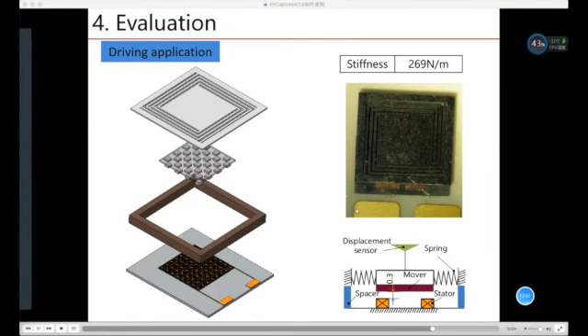In order to test the application of this actuator, we apply this mover with the planar spring like this, and then assembled a micro actuator. The planar spring stiffness is 269 Newton per meter, calculated by the finite element method. This shows the picture. And then to measure the displacement, we use a displacement sensor.